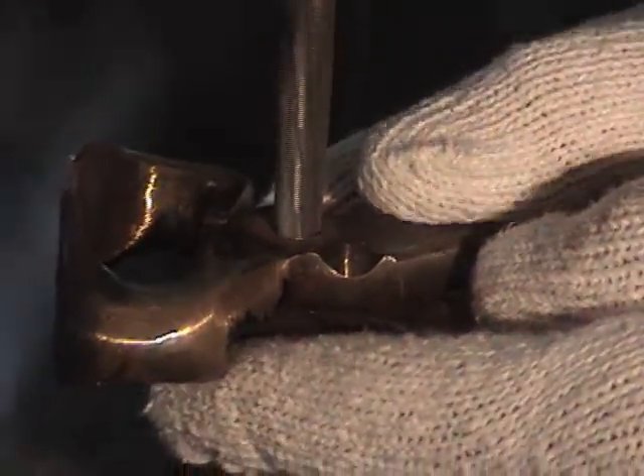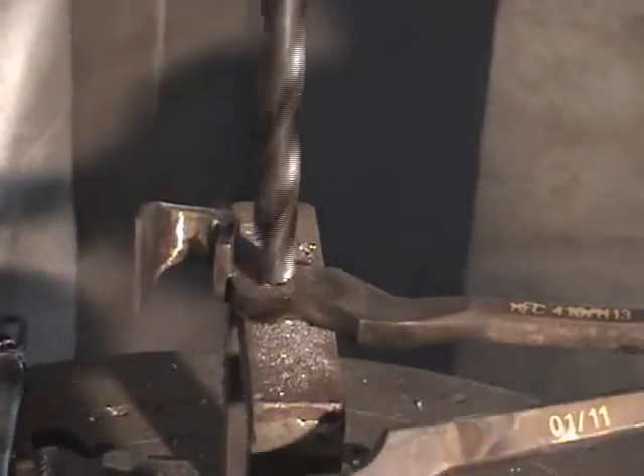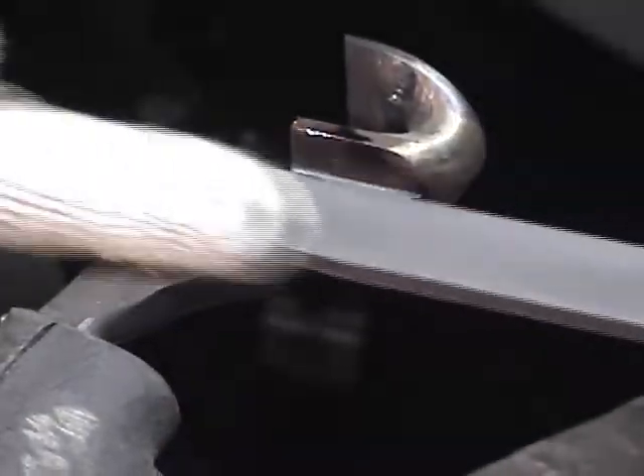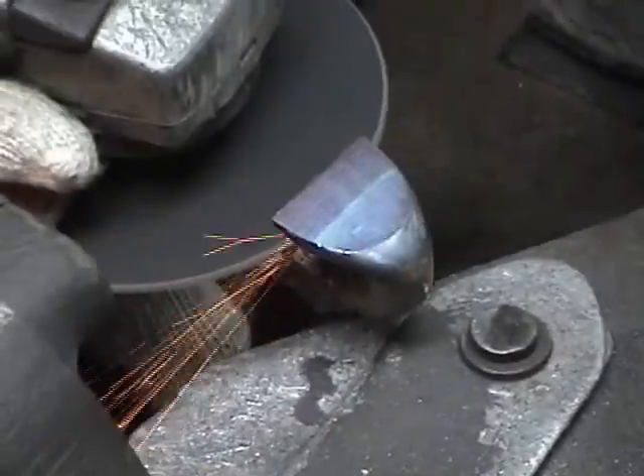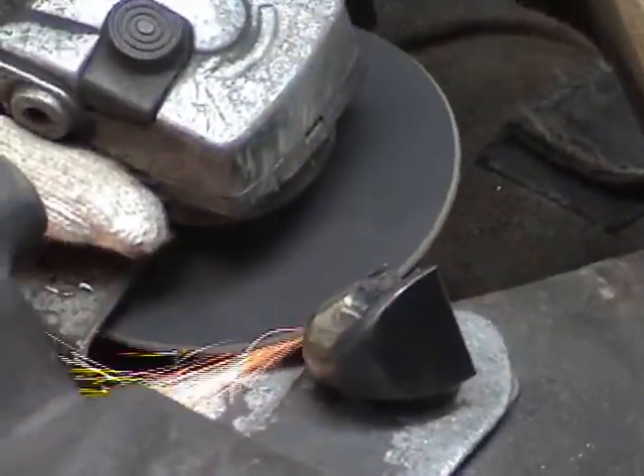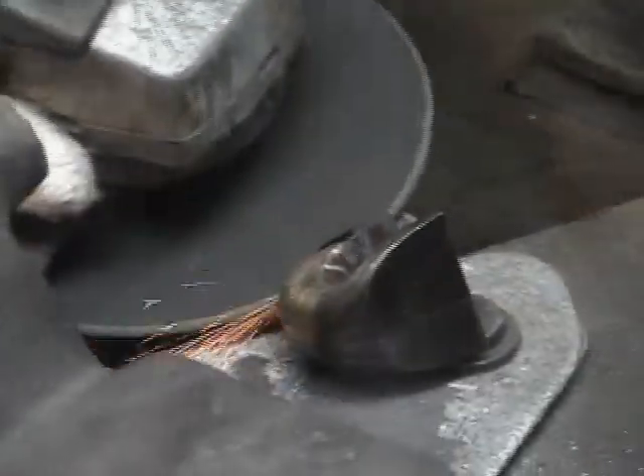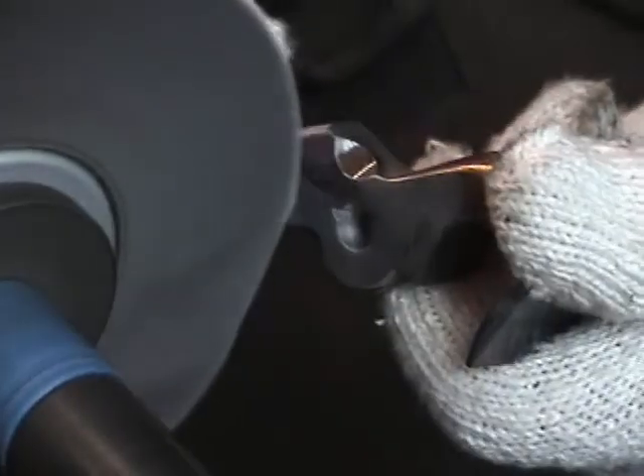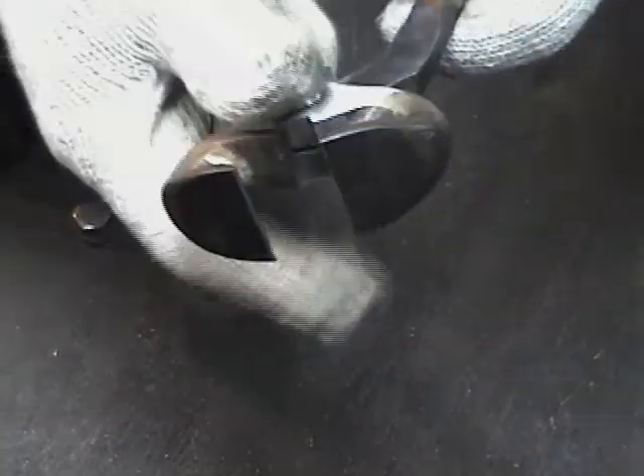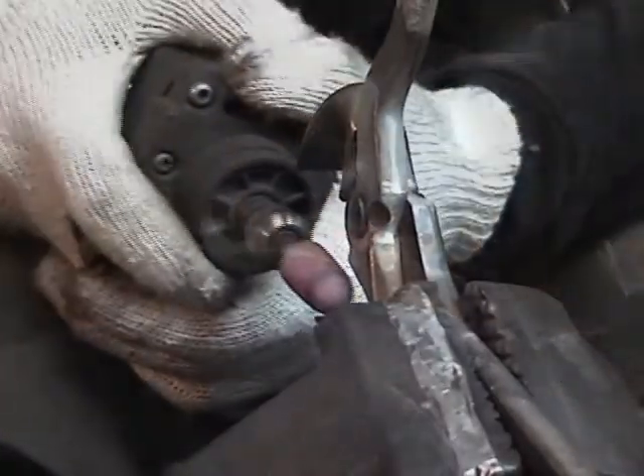In the next scene, it appears that the rivet hole is being re-drilled. Actually, the hole is now being reamed to a very precise diameter to perfectly match the rivets. We have found that to get proper rivets of the proper material and of the perfect diameter, we have to make them ourselves. We make each rivet separately on a shop lathe, and the rivet must perfectly fit into a measuring die that we have made for this purpose. We then insert the rivet into the rivet hole and heat the rivet before peening the rivet.